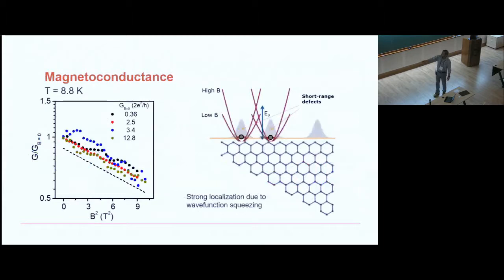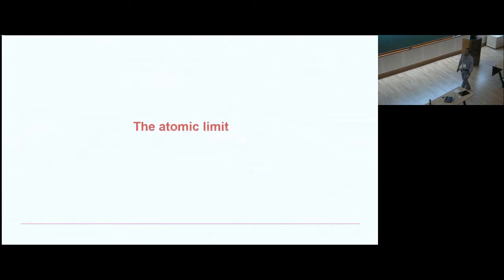Okay. Very interestingly, if I apply a magnetic field, I completely destroy the universal quantization. As you can see, that's probably because you have the edge disorder here, which as soon as I apply a magnetic field, I localize my electrons along the edge disorder, and that leads to a strong localization due to the squeezing of the wave function itself. However, before I move on to the next topic, there's something really interesting, and I was really excited by this. This was pointed out to me by Vijay Shenoy and his student Adip.